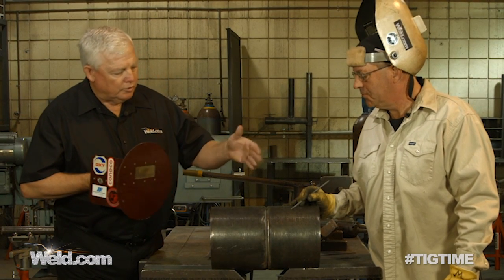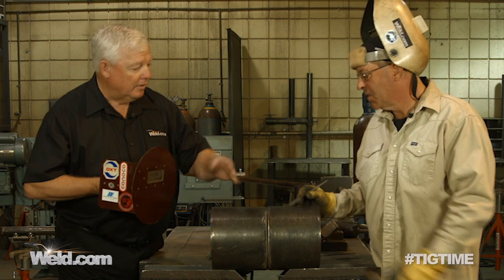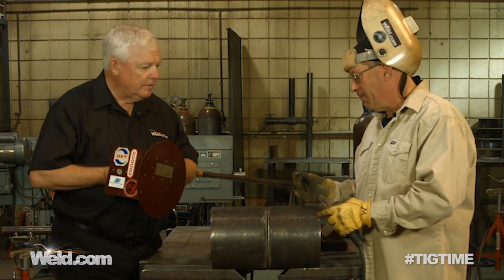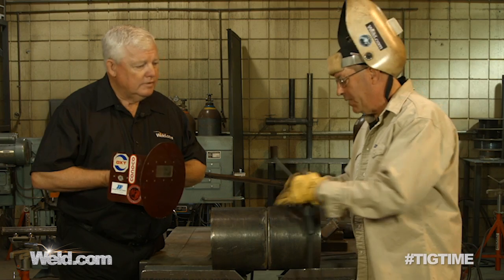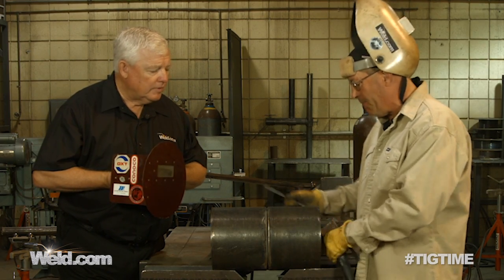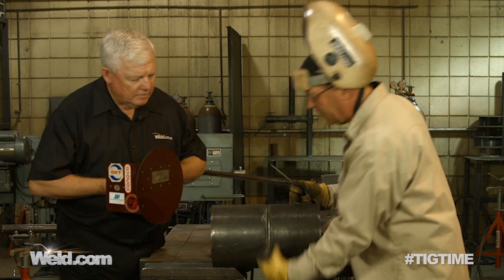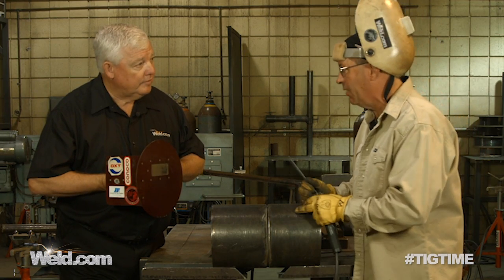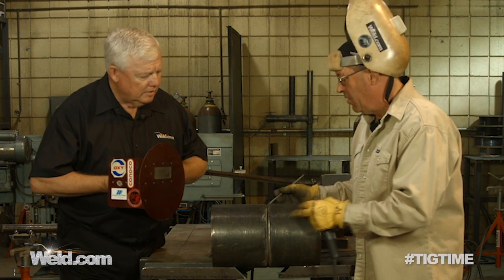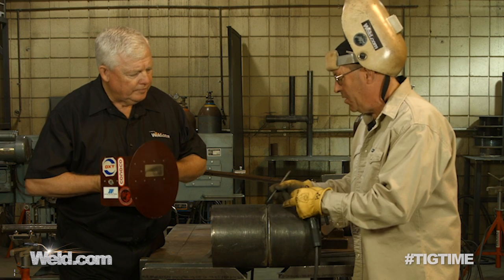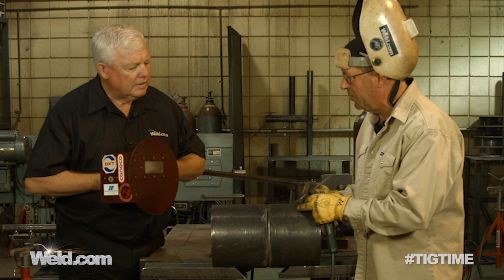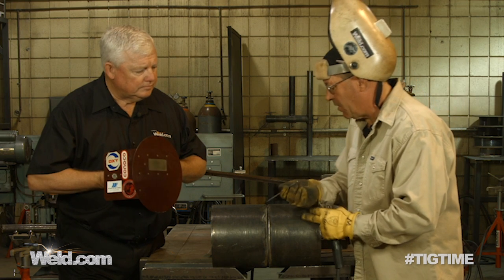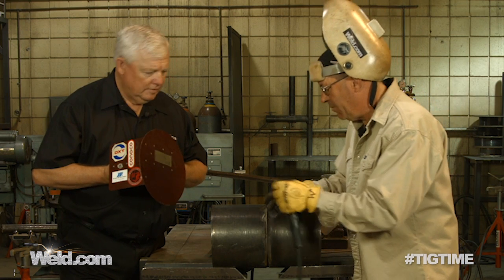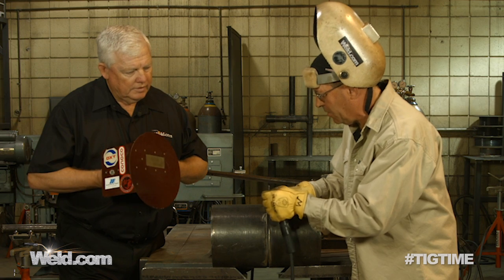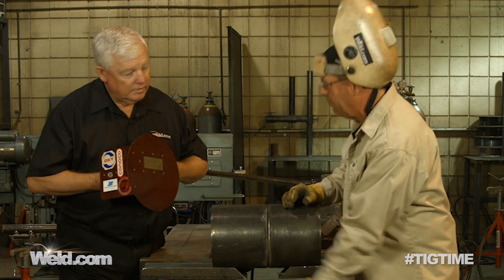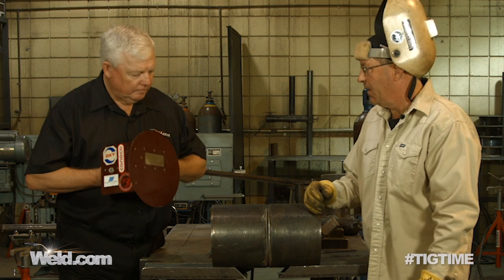Okay, so you've got your root pass you're going to put in right now. Mm-hmm. And what's the diameter of filler? I have an 1/8-inch 6010. My pipe is already pre-tacked up here at the top and the bottom, and I have one over here on this side. I've left this one open because I just don't want to grind it. I don't need to. Okay. Normally, if I had my 4 fit-up tacks in here, I would feather the starts and the stops. Okay, but I'm just going to start up here on top of this tack, and I'm going to fall down over the top of this keyhole, reestablish, and just fly down through here.